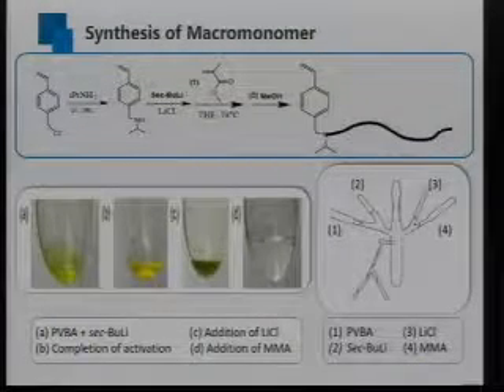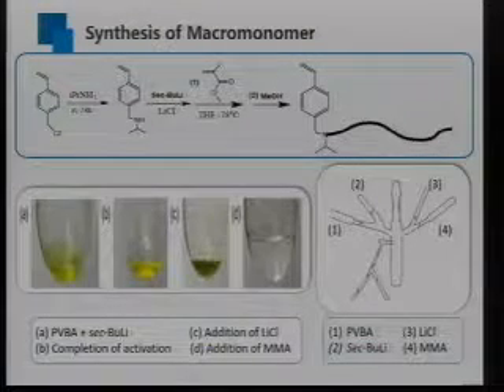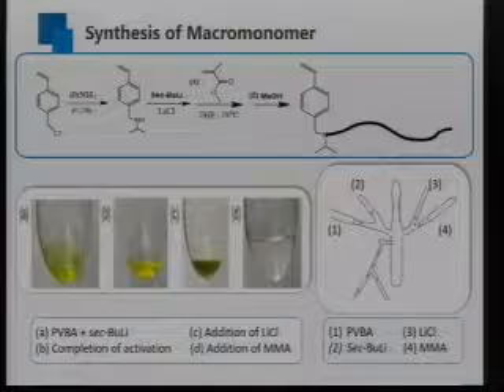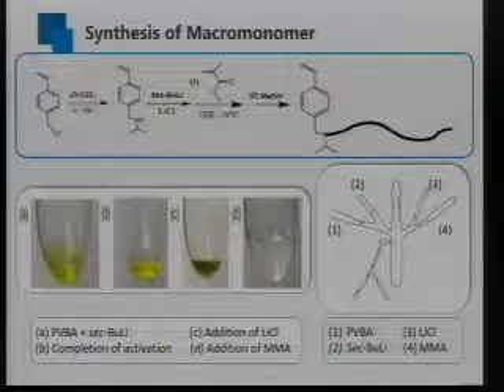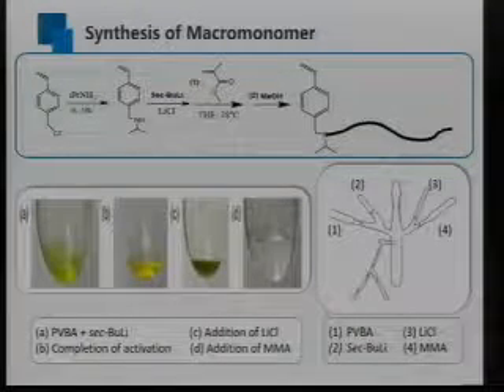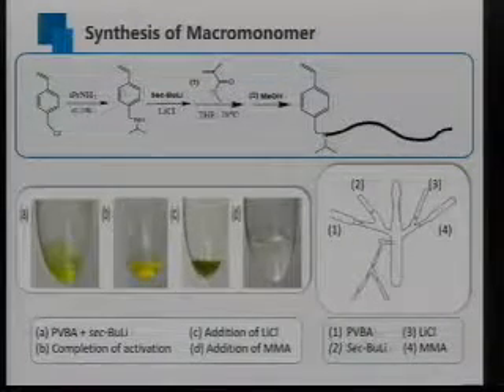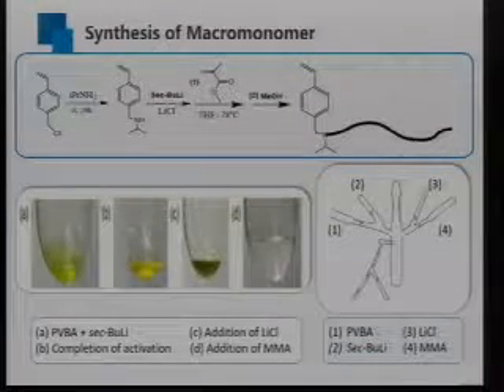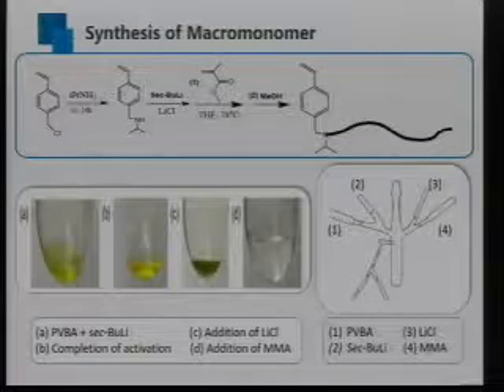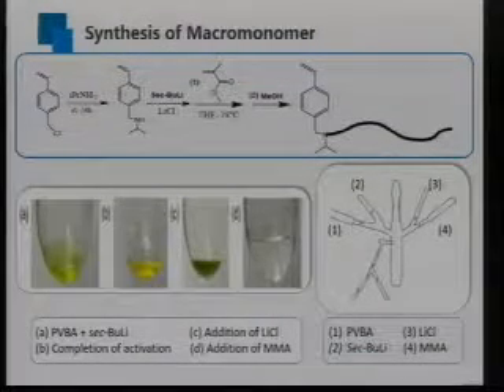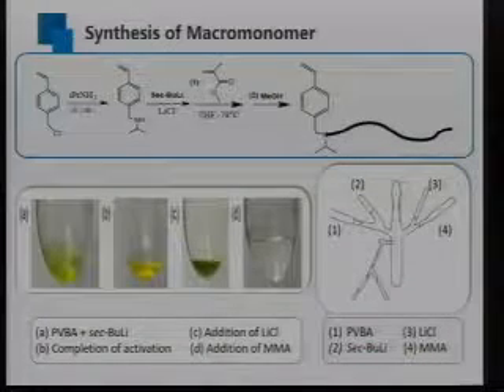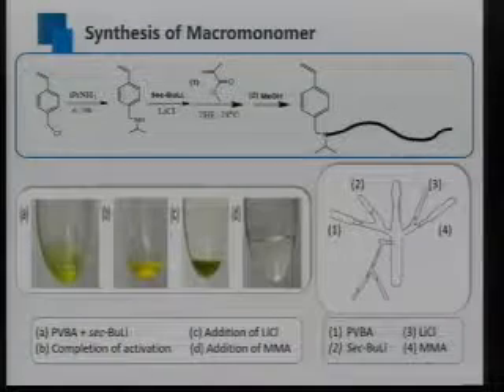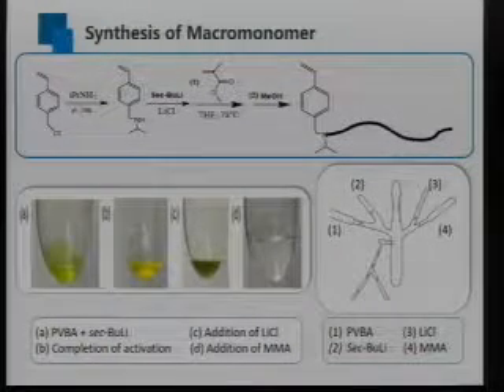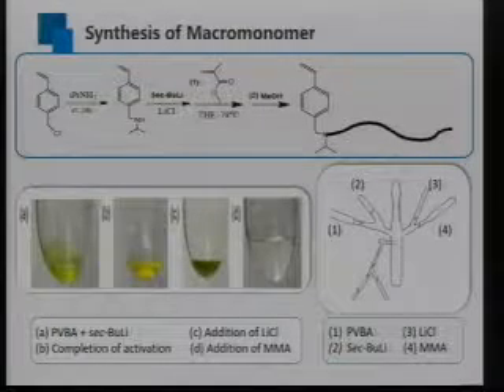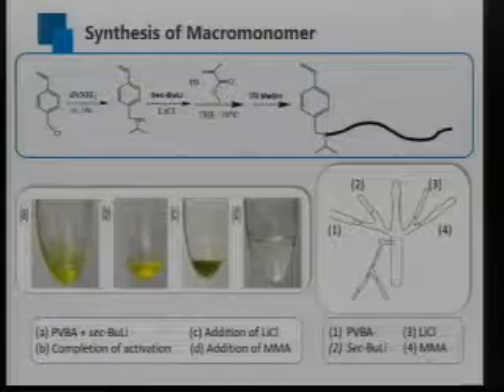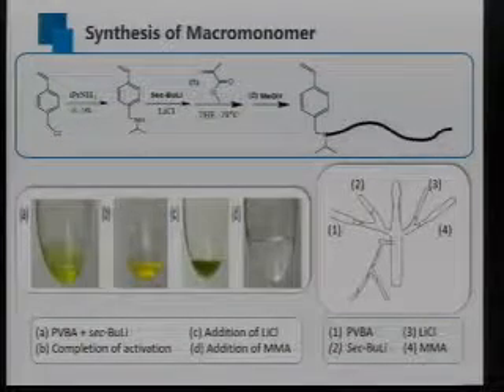And after the activation, that is the combination of sec-butyl lithium with the PVBA, it forms a light yellow color, which turns to a deep yellow color after 30 minutes, which means the completion of this activation. Then lithium chloride was added to the system to avoid the attack of this nitrogen anion on the carbonyl group. This is a side reaction that will make the polydispersity very broad, and it forms this kind of green color. And after the addition of the MMA monomer, the solution color disappeared with the increase of the viscosity, which is the common phenomenon for living PMMA polymer chains.